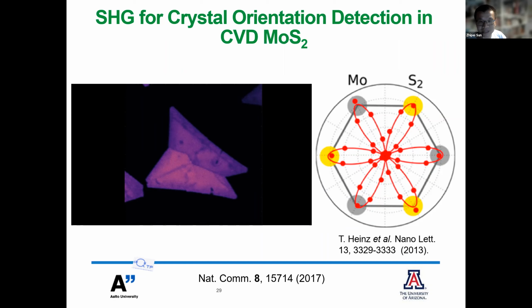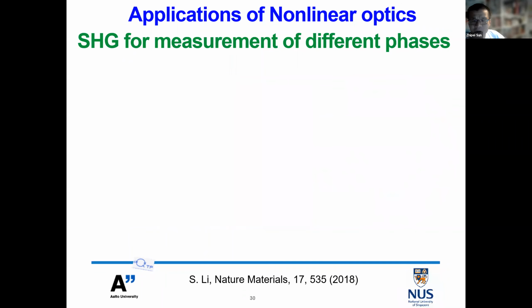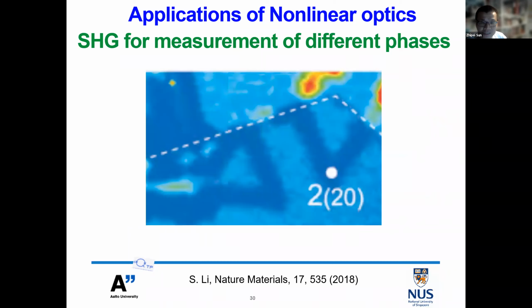At the moment, second harmonic generation is one of the most effective ways to measure the twist angle inside of these heterostructures. Second harmonic generation also can be used to measure the different phases of the flake grown by the CVD method. This is the result. For example, you can clearly see that this is the monolayer flake. This is the monolayer region, and this is the bilayer region.